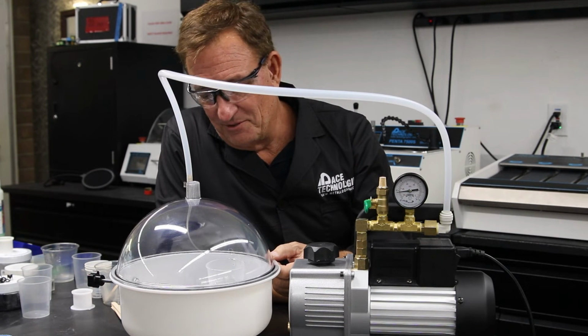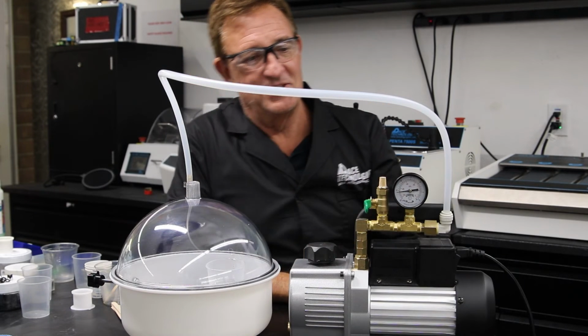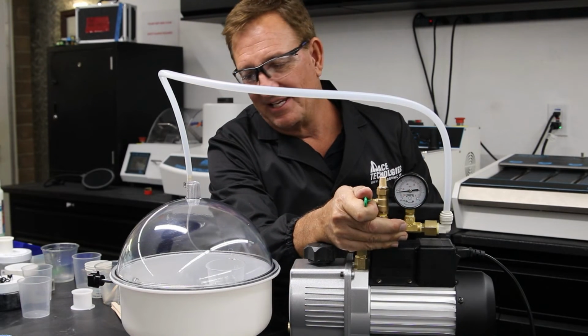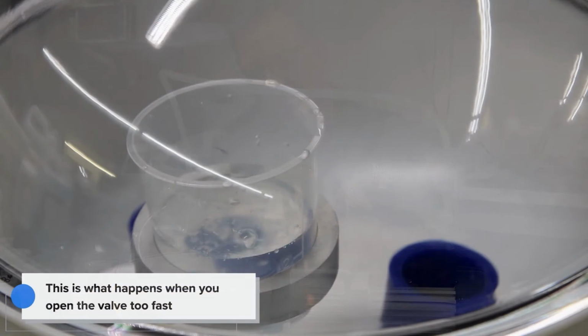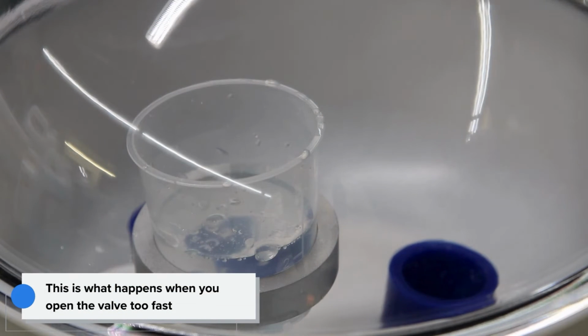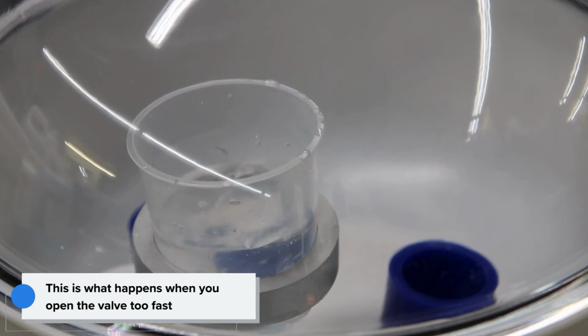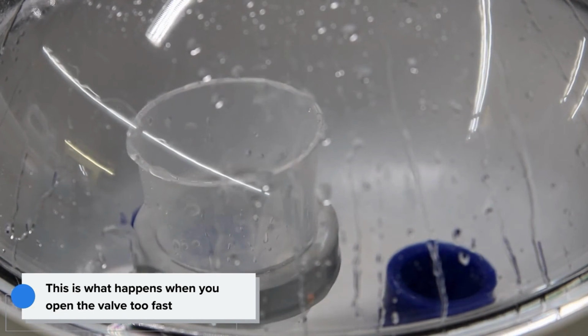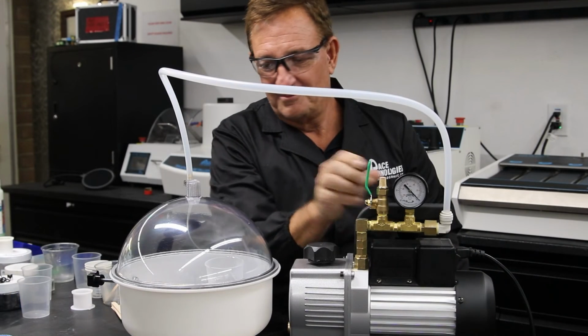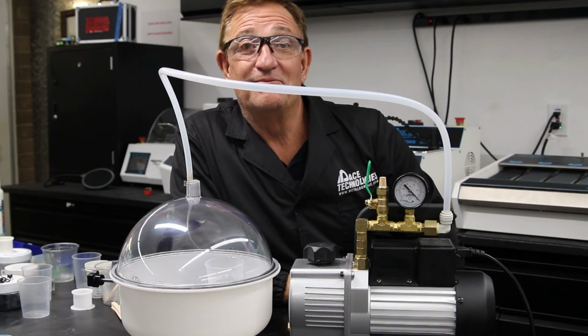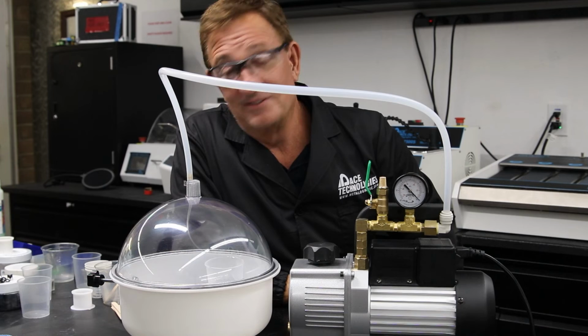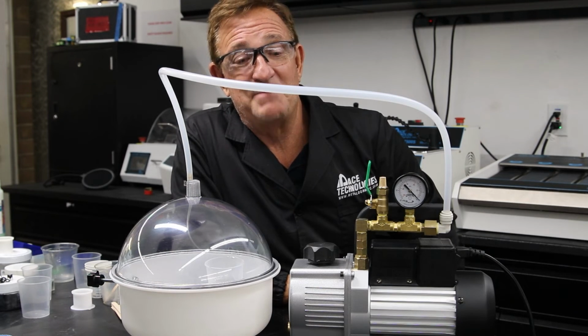So now that we've poured the resin, what we want to do is slowly open up the valve. If we open up too fast, it will flood the chamber with air, and it will cause the resin to splatter all over the inside of your chamber, so you don't want to do that. And now we're just waiting for the resin to cure, and we have vacuum impregnated mounts.